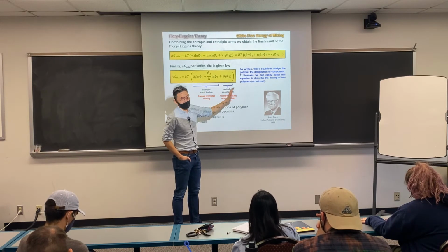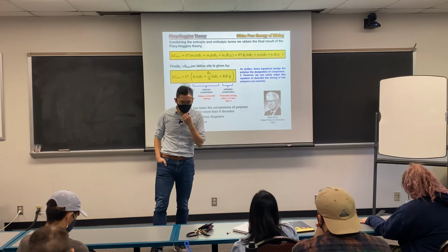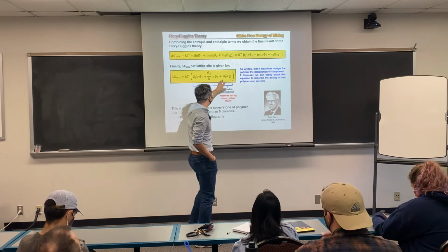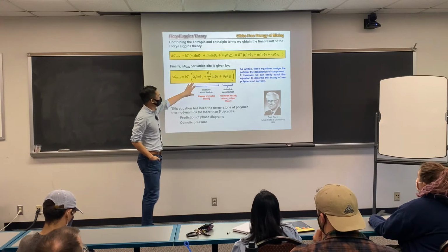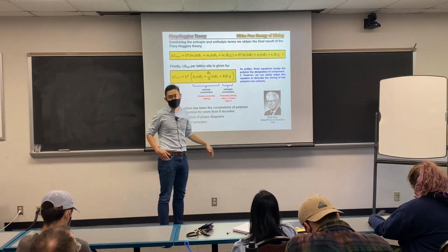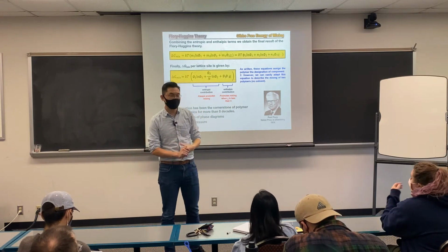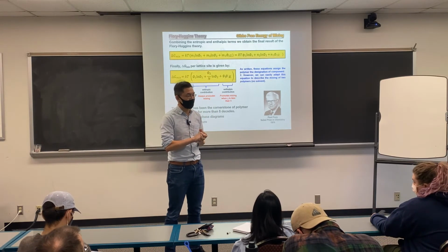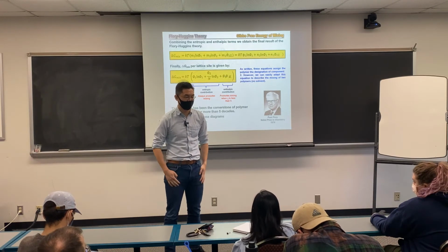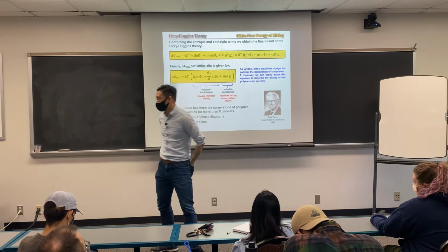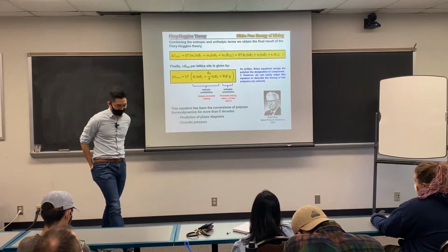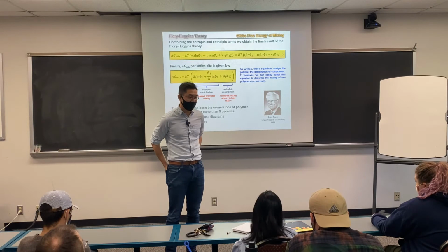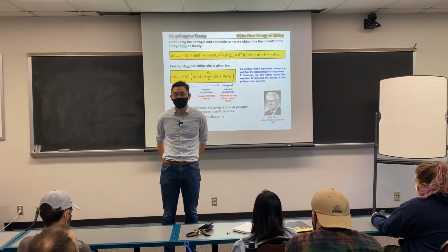Depends on the specific scenario. But in the other two cases, let's say your chi equals 0, then this second term will be equal to 0. And then, as we know, entropy always favors mixing. So you're always going to have a mixture. Your polymer is always going to dissolve in solvents in this case. Of course, if you have a negative chi, it will be even better, because then your enthalpy favors mixing, and your entropy also favors mixing. Okay? So those are a few scenarios. And we will talk later about how, since we know that chi is so important, it's very important to get an accurate chi and measure the interaction parameter between your polymer and solvents.